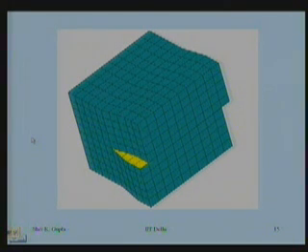In other words, if you start from here, I went in an anti-clockwise fashion. Go in the clockwise fashion. You start here, go in the plane below, reach here, come there, reach here, go to the second plane there, reach here, go there, go to the third plane there, reach here. See, you are able to go inside the crystal.